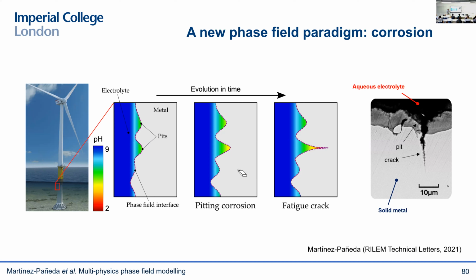So I think there's basically two challenges here. First, you need to model, again, an interface that is evolving, that is complex. And the second thing is that this is a very strongly coupled problem, because the shape of those pits, the shape of that interface, will be driven by the local chemistry and mechanics. But the local chemistry and mechanics themselves are dependent on the shape of those pits. So we know that the pH will be very different inside of occluded electrochemistries and in small spaces. We also know that, of course, the sharper your pit, the higher the stress concentration, and that will also affect the corrosion kinetics. So everything is very strongly coupled, and you need to resolve all of these physical processes if you want to be predictive.